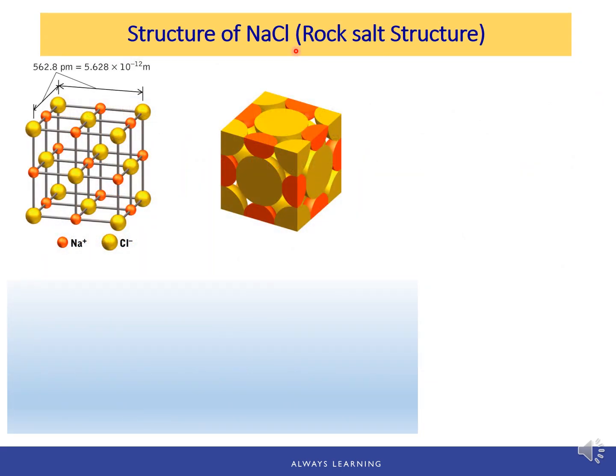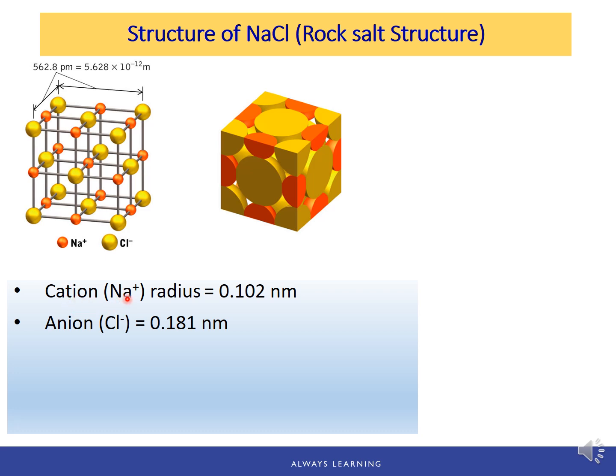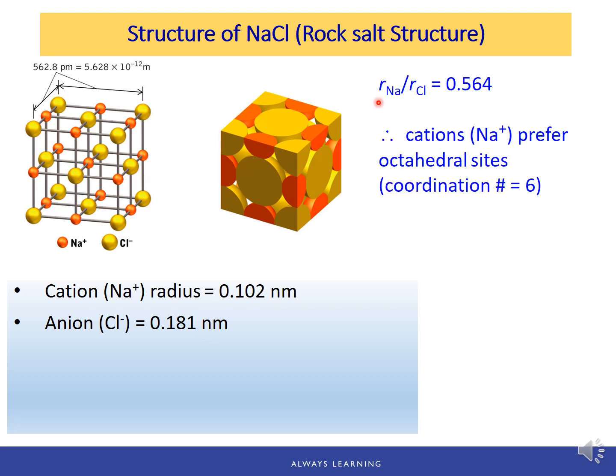The most common AX crystal structure is the sodium chloride, or rock salt, structure. The radius for the sodium cation is 0.102 nanometer and the radius of the anion is 0.181 nanometer. So we can calculate the ratio of RC over RA, which is 0.564, and it is roughly between 0.414 and 0.732. Based on the table of critical ratios, we can find the coordination number has to be 6, which means the cations prefer the octahedral sites.